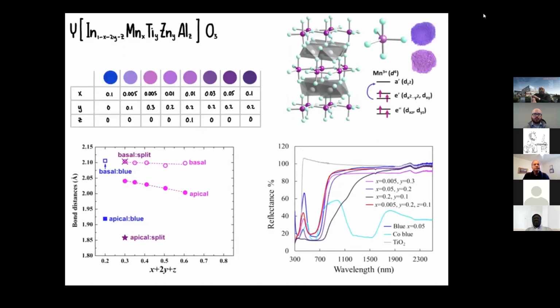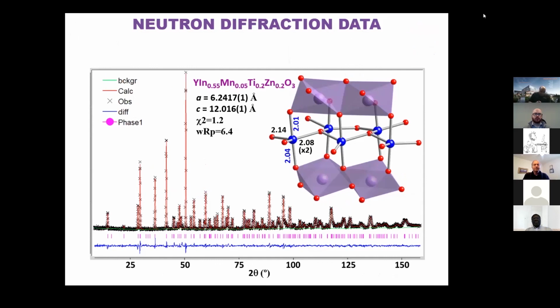So along the way, he had come up with the idea, what if I change the indium and manganese and replace that with indium, manganese, titanium, zinc, and aluminum? Just put something else in there, see how that changes. And guess what? He was able to come up with not just blue for very small values of x, but he also came up with these rich purples. And the rich purples, this is where he really needed to understand where this color is coming from. So he brought these samples to NCNR to do neutron diffraction measurements, so he could figure out what the dependence was of the spacing of the center compound from the apex oxygen atoms. And this is just diffraction data.